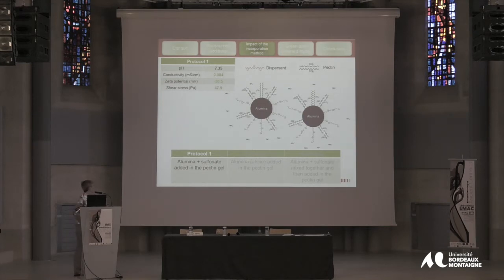For interpreting this data, we think that there is a competition between the adsorption of the dispersant here in red and the pectin, the binder, okay, as shown here. So we have a shell around this alumina particle, but not too much interaction between the polymeric molecule.